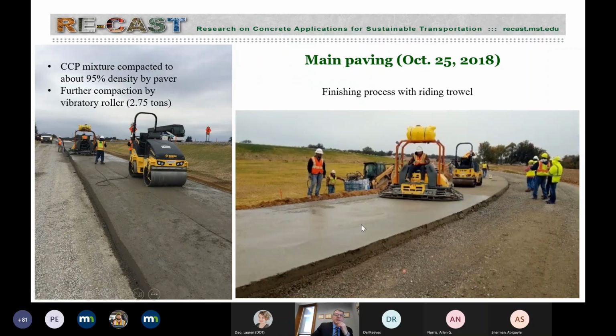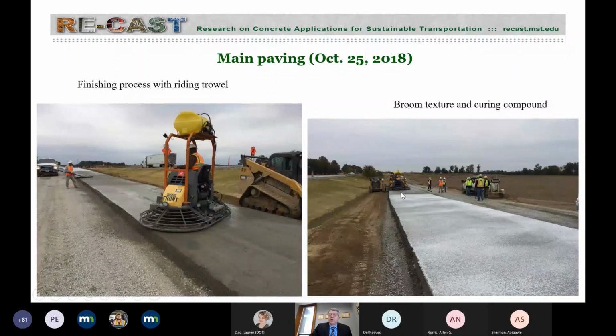So the compaction was specified. You consolidate, you compact it until you reach an in-situ density of 95%. And this was done. And then you have this admixture, which is the finishing aid, a proprietary admixture that was used. And you could see the pasty type of surface apparent. This is without it, this is with it, and then the riding trowels are going around, ensuring that we have a closed surface. And then curing compound was applied, and that's how the concrete was cured.